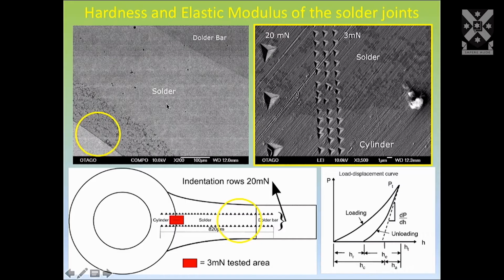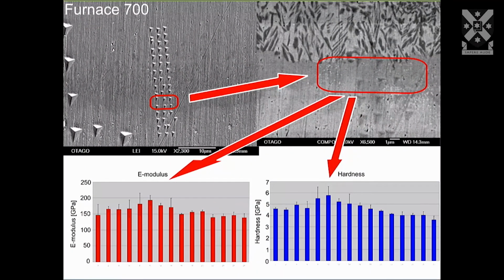Running parallel to this, the group took some original components, a bar that you see over here, a gold cylinder, and a solder here. And this is shown as a bar there, the solder, and the gold cylinders down here. We then soldered them together, polished them up, went to the scanning electron microscope, and at the same time, we nano-indented them. These little indents you see running here allow us to measure the modulus of elasticity, which is stiffness, and the hardness of the various components across the joint. What we found was that just inside the edge of the cylinder was a gray zone that we observed, and when we looked at its hardness and modulus, it was significantly higher than the rest of the components of the system. And this was quite interesting.